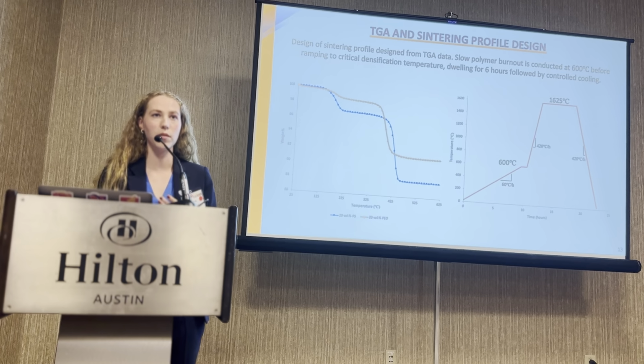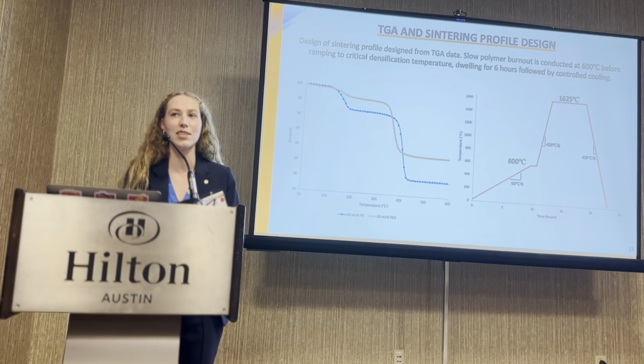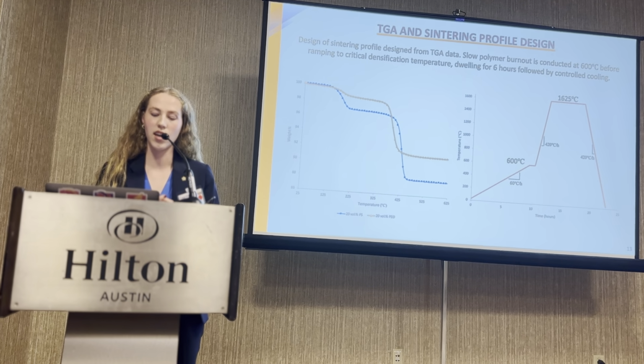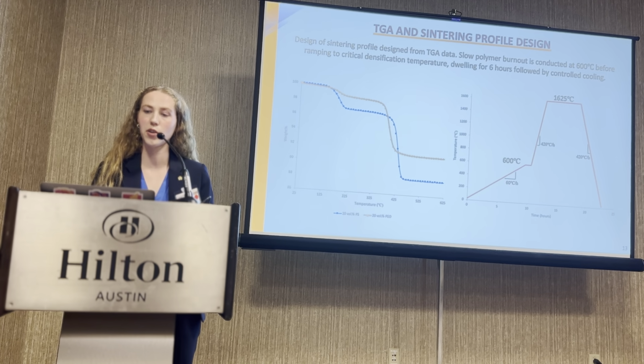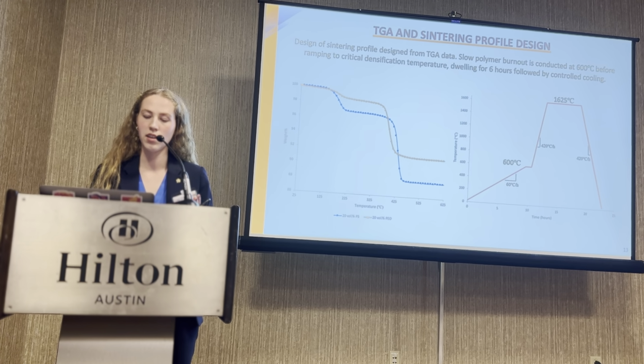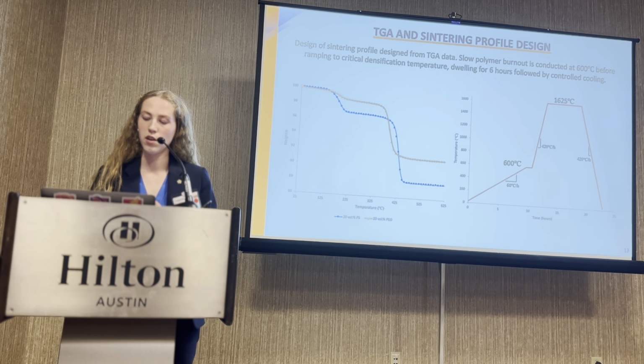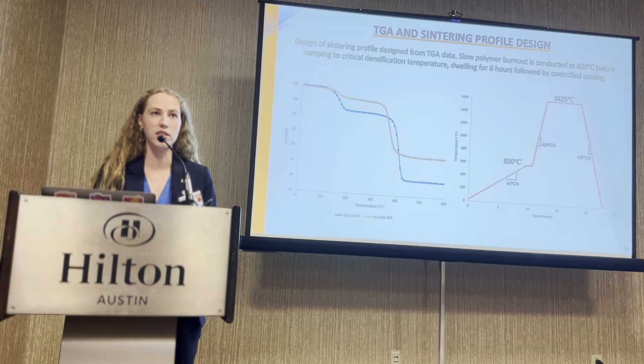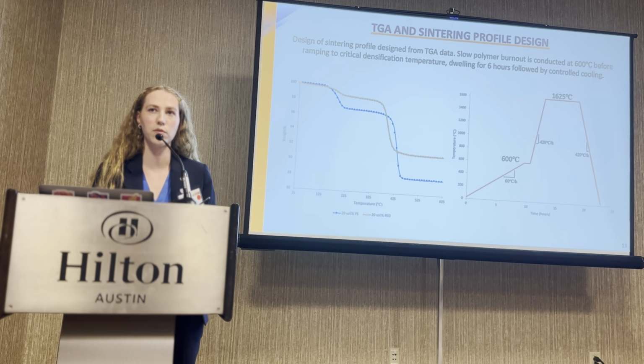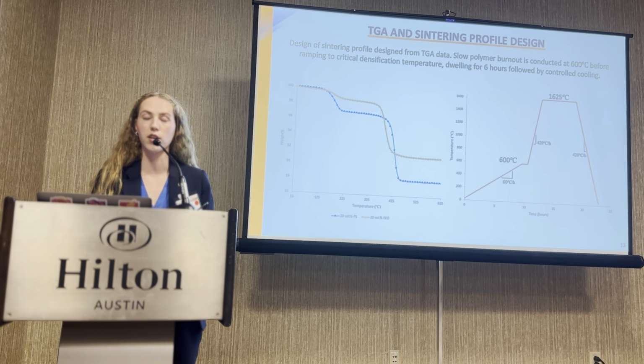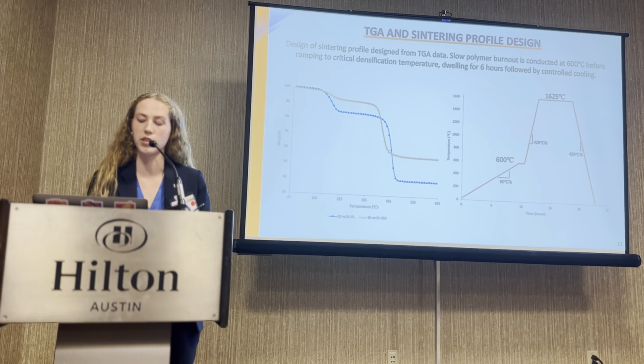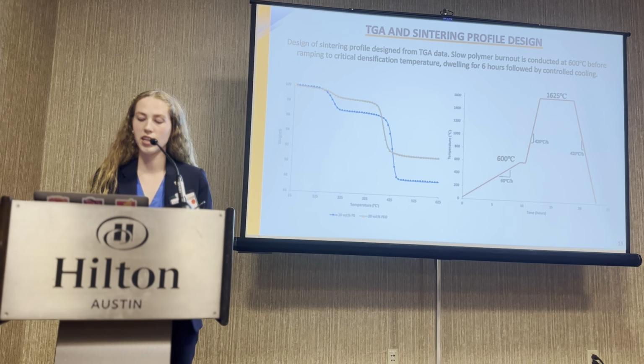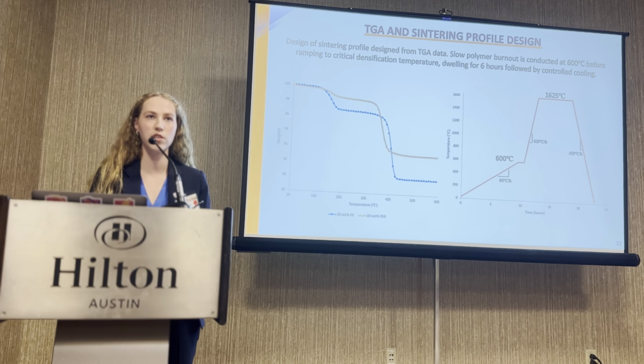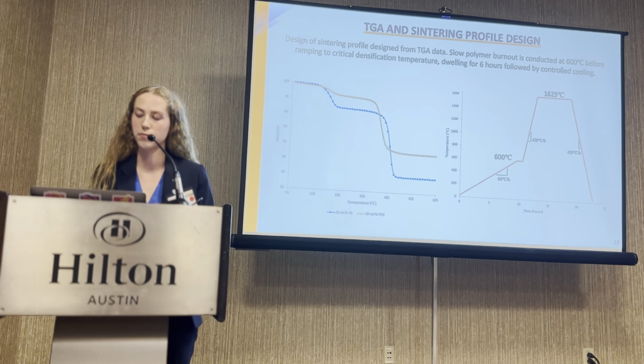We use thermogravimetric analysis to design our sintering profile, and by observing when the polymer burnout occurs, we designed this burnout profile. First step is the polymer burnout at 600 degrees Celsius. It removes all of the polymer and it leaves behind the carbon structure that supports the form during sintering. The second at 1625 is densification, and then we conclude with controlled cooling.